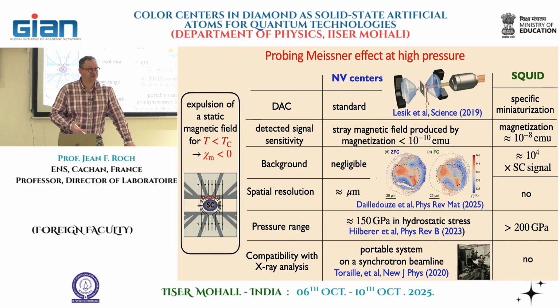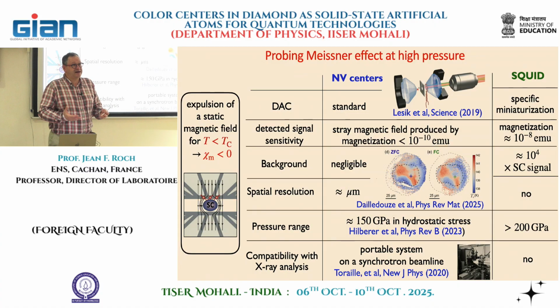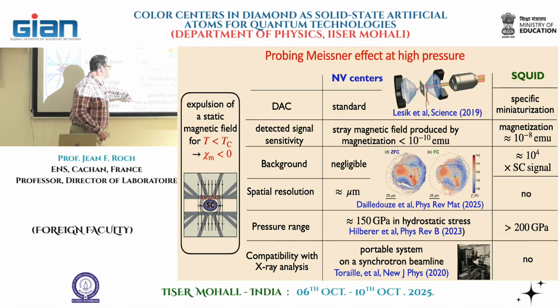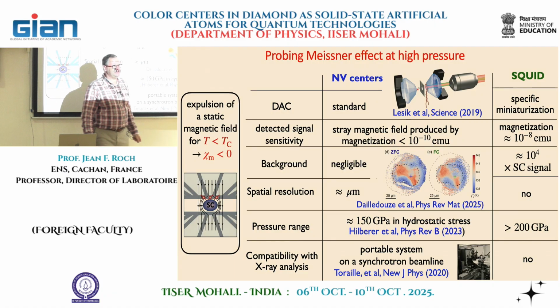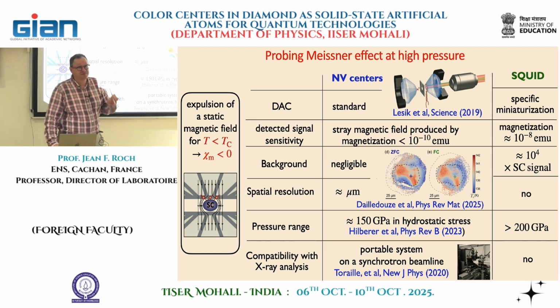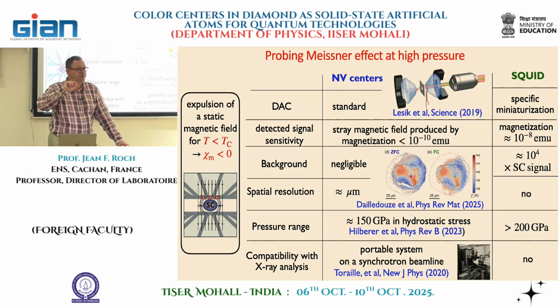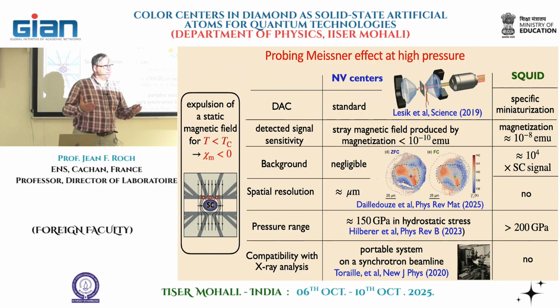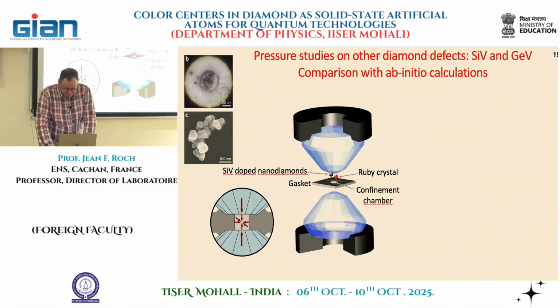And I think this is very important, because as soon as you get some materials, you want to analyze the structure. And now with 4th generation synchrotrons, you achieve micrometer resolution in X-ray diffraction patterns. You can really determine the structure of a sample with this micrometer resolution. And having a tool that measures the magnetic response with the same spatial resolution is something that will be very complementary for all these measurements.